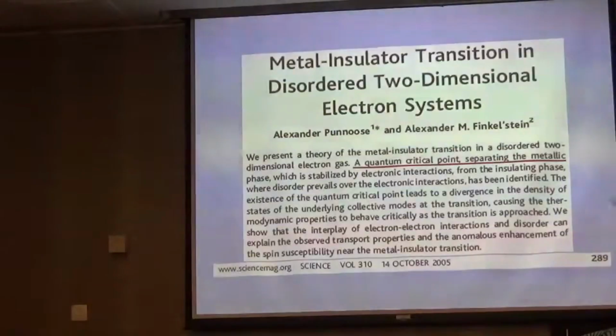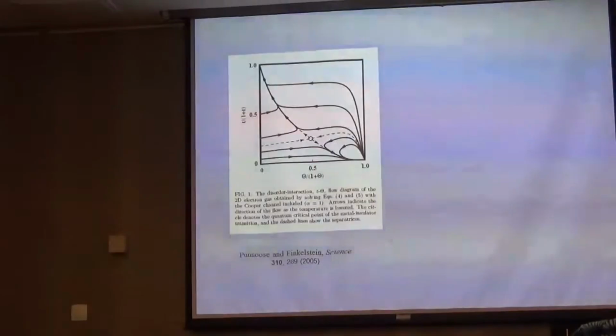They show that there is indeed a quantum critical point separating the metallic phase, which is stabilized by electron interactions, from the insulating phase where disorder prevails. And then they made some quantitative and qualitative predictions. Namely, they predicted what the phase diagram should look like.